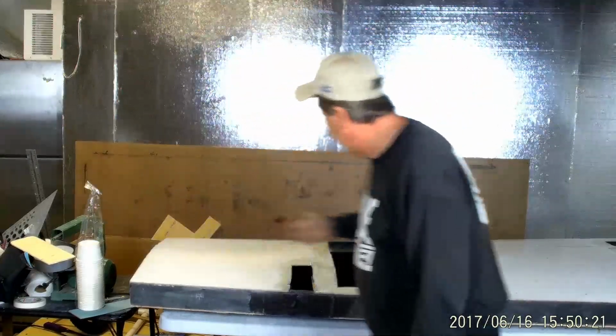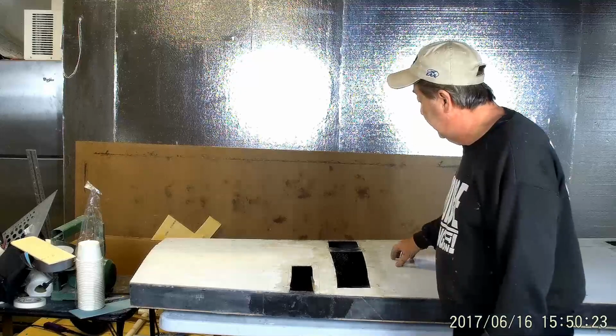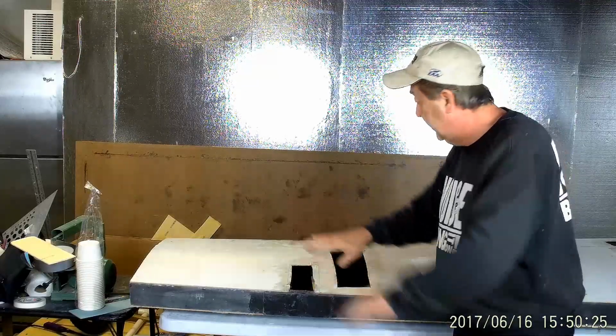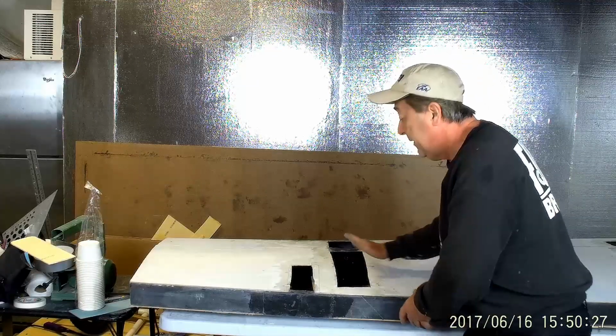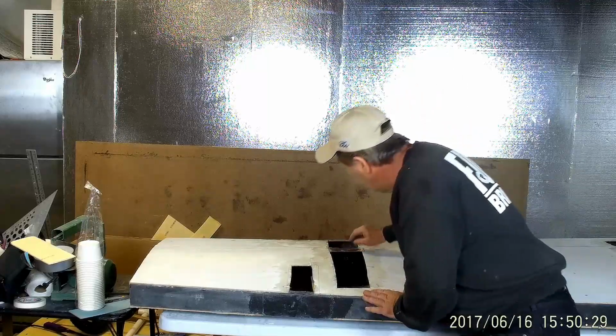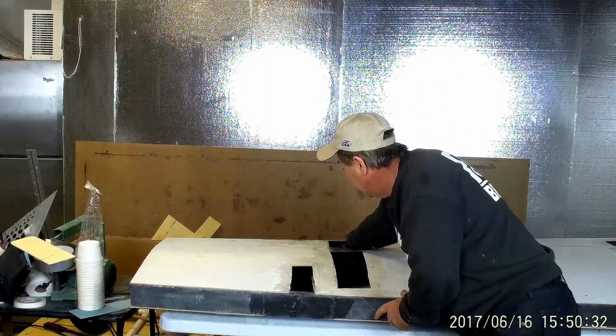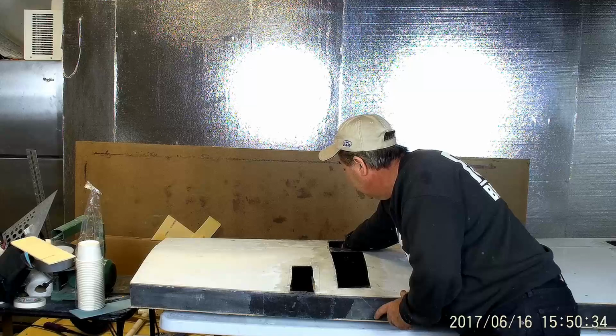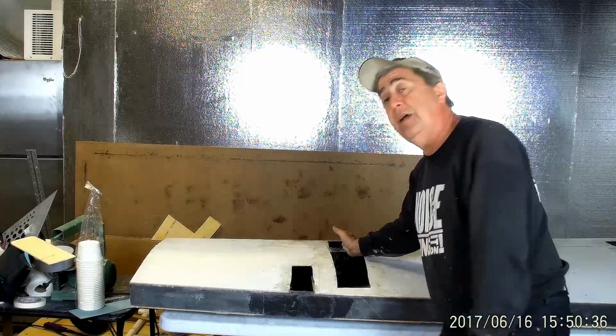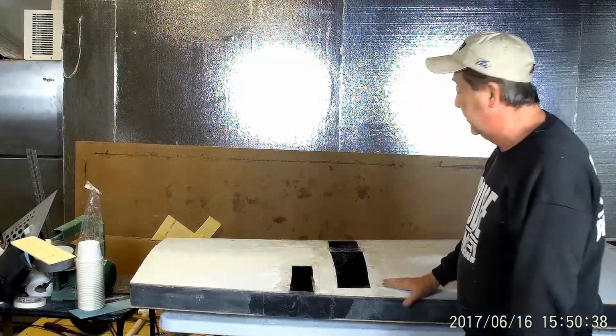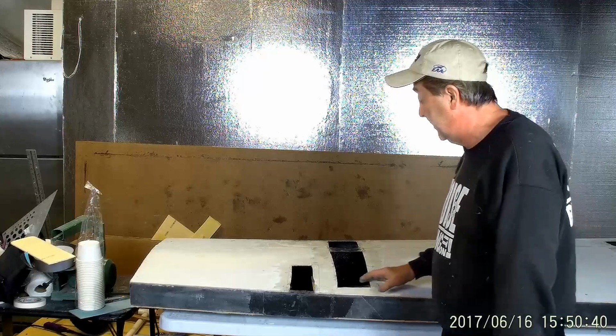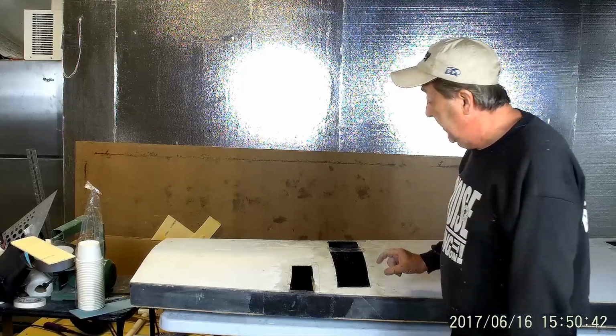This tip hit the ground. The other end was still semi-attached, and it just took a kink right here. Interestingly enough, the wing broke or got damaged just outboard of the leading edge tube. The leading edge tube ends right here, and the damage is just beyond that leading edge tube. So it's right where there was a stress riser, and that's to be expected, but interesting to see.